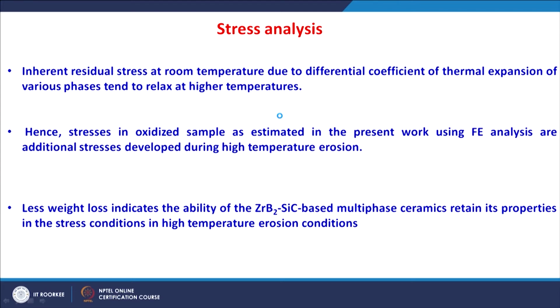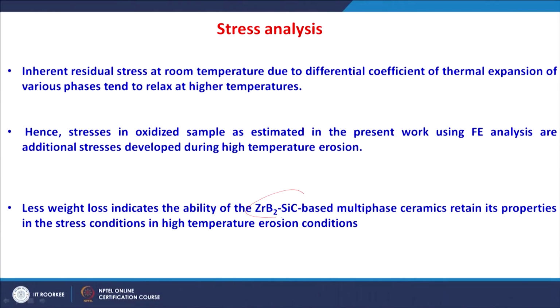So, we must understand there are certain inherent stresses generated. There are certain inherent residual stresses at room temperature because of the difference in coefficient of thermal expansion of various phases present in the material, but these stresses tend to relax at higher temperature. So, the stresses in the oxidized sample as estimated in this work using this finite element analysis are additional stresses developed during high temperature erosion. We can also see there is very little weight loss because of this erosion. This very little weight loss indicates the ability of this zirconium diboride silicon based multi-phase ceramics to retain the properties in the stress conditions in the high temperature erosion.